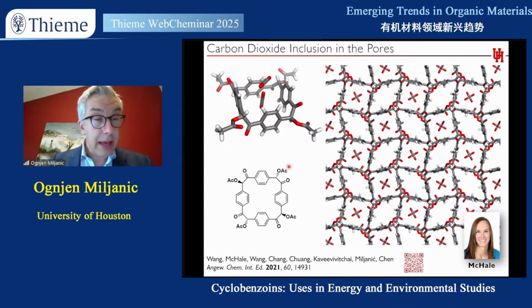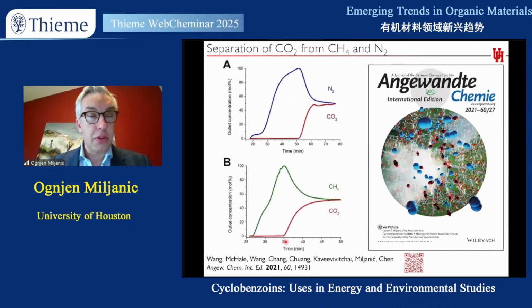Now, this cyclotetrabenzoin acetate is made in two steps. One is the benzoin condensation, which is done in water and alcohol solution. The second one is acetylation, which is done in neat acetic anhydride. This is a pretty easy and pretty scalable synthesis, and Corey was able to produce 15 grams of this material in a single batch. And so this allowed us to construct adsorption columns filled with our material as a neat adsorbent, and use those columns to separate carbon dioxide from nitrogen and carbon dioxide from methane in these breakthrough experiments.